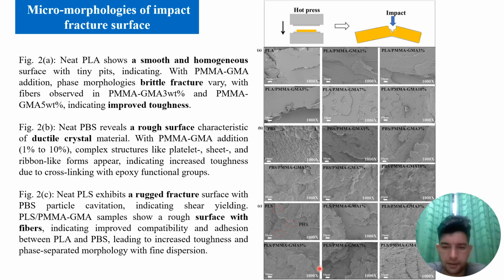So from the SEM images we observe that the PLA surface is very smooth, and this one is very rough. By combination the surface is changed, but by adding this one the surface is changed even more, which can easily show that some properties will be changed, so the surface becomes more rough and more toughened.